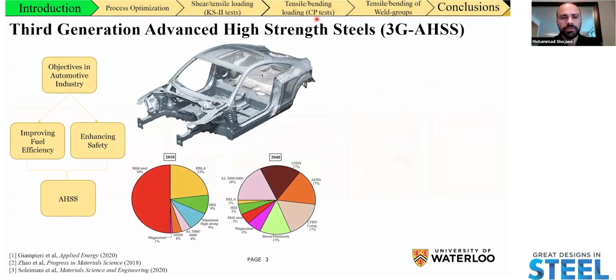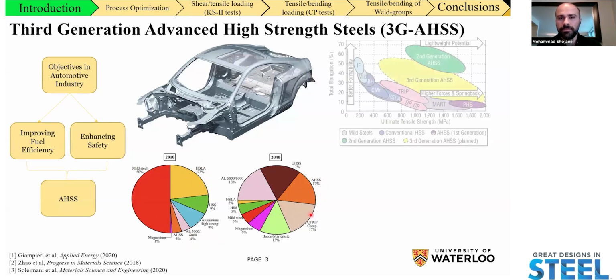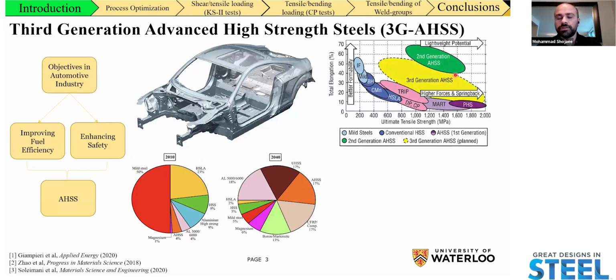If you look at the pie charts in the middle of the screen here, we can see that between 2010 and 2040, so in around 30 years, it is estimated that the usage of steels with relatively low strength, such as mild steels or high strength low alloy steels, is going to diminish. And at the same time, we're going to get much more adoption of steels such as advanced high strength steel or ultra high strength steels. Now, the main reason for this trend is the properties in terms of strength and ductility that the advanced high-strength steels are able to provide us.